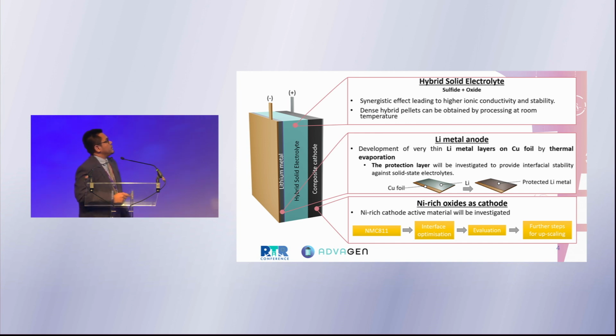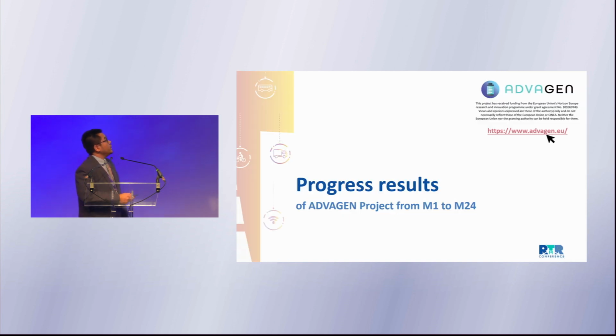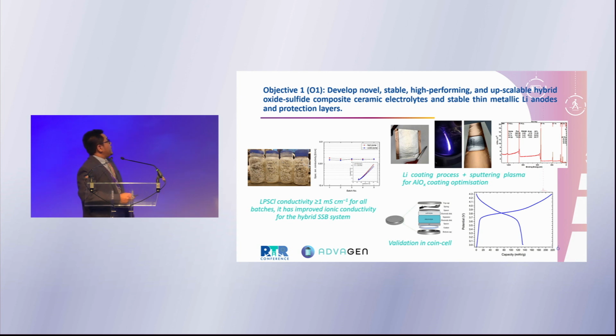This nickel-rich cathode, we want to try to produce in Europe. That's why we involve Cerpotech from Norway and also IREC to evaluate the NMC 811 that is produced. And this is the progress result. So far, the LPSCl conductivity that we got is already more than our KPI, for all batches produced by TU Braunschweig. And once we mix it together with the LLZO, it has improved ionic conductivity for the hybrid solid-state battery system.